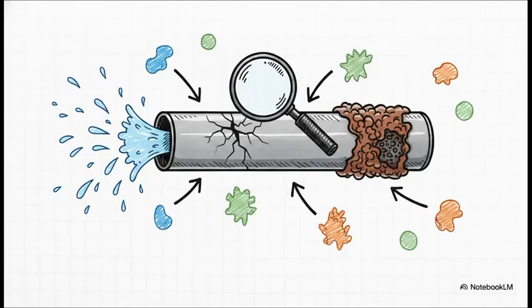So if we pull all this together, we can directly link these exact chemical suspects to the specific mechanical failures they cause. Carbonates and CO2, they set the stage for FAC by dropping the pH. Sulfates, they hide under scale to supercharge UDC. Chlorides and sodium provide the exact toxic environment you need to crack stressed metal via SCC. And those iron and copper ions are the initial architects, building the porous crud that allows UDC to take hold in the first place. Every mechanical failure we're looking at here starts with a chemical imbalance.